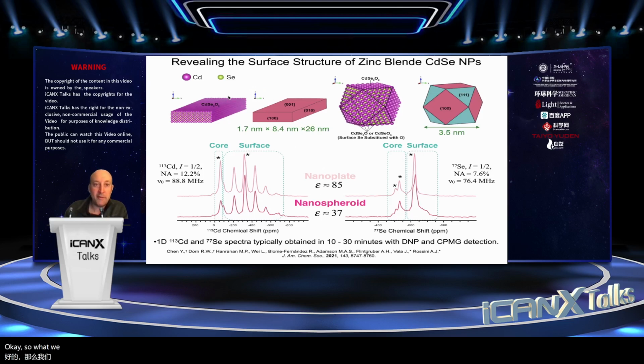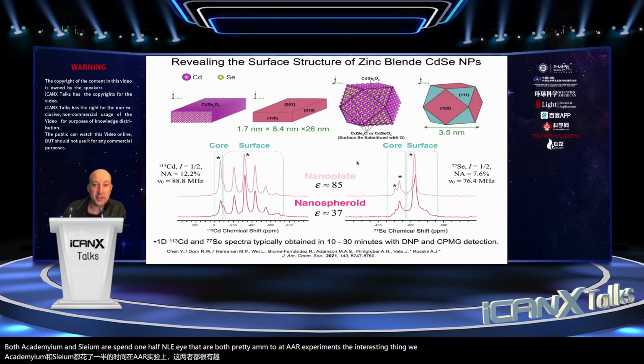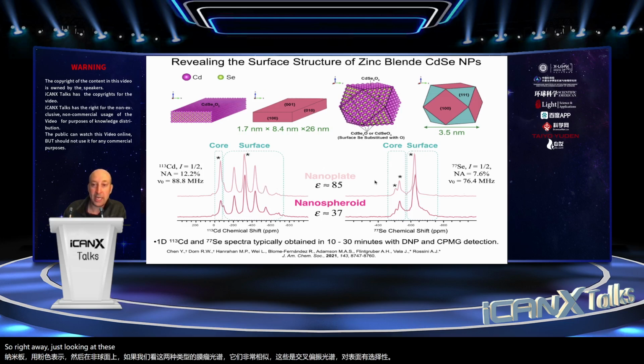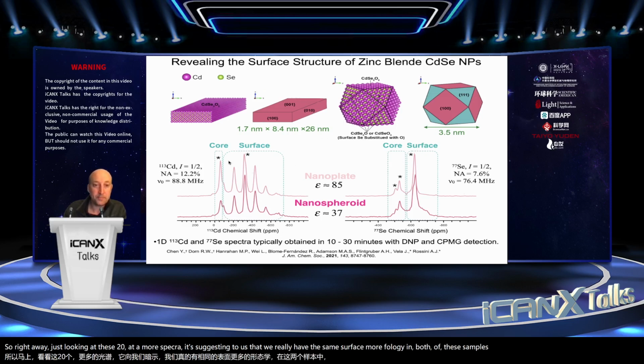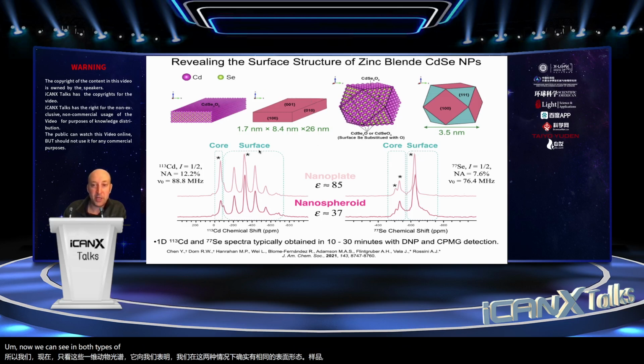Okay, so what we have here are some cadmium DNP enhanced NMR spectra and selenium NMR spectra of the 2D cadmium selenide plates and then the spherical cadmium selenide nanoparticles. Now, both cadmium and selenium are spin 1/2 nuclei that are both pretty amenable to NMR experiments. The interesting thing we can see is that when we compare the nanoplates, which is shown in pink, and the nanospheroids, if we look at both of these types of NMR spectra, they're very similar. And these are cross-polarization spectra that are selective for the surface. So right away, just looking at these 1D NMR spectra, it's suggesting to us that we really have the same surface morphology in both of these samples. Now we can see in both types of spectra, both surface and core NMR signals, and I can explain how we can assign those later on if you have interest.